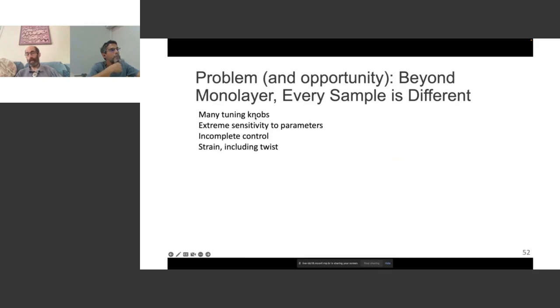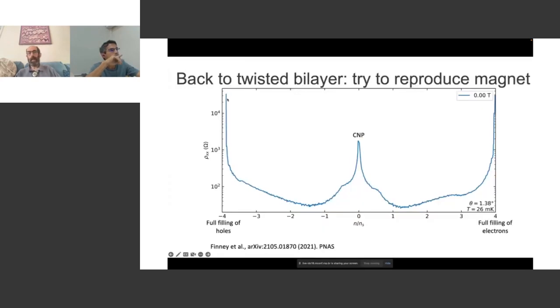We ended up having something that appeared to be at a substantially larger twist angle. We're now questioning whether we were really right about that, but it's a small twist angle between two graphene layers. And you see that there's a peak in resistance at the charge neutrality point. It's pretty normal, it's not what you'd expect for alignment with boron nitride. And there aren't very strong features until you completely fill or completely empty the band.